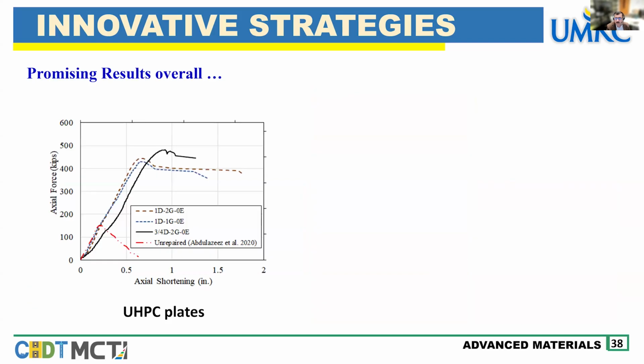And in general, as you can see here, using the UHPC plates, this is the unrepaired one, this is the corroded one. And we were able to get the capacity of the repaired one up to 3 times the unrepaired steel H pile. So we're using the ultra high performance concrete plates.